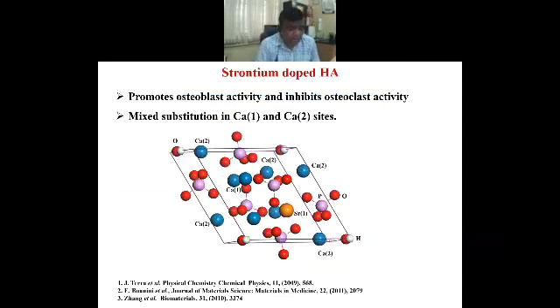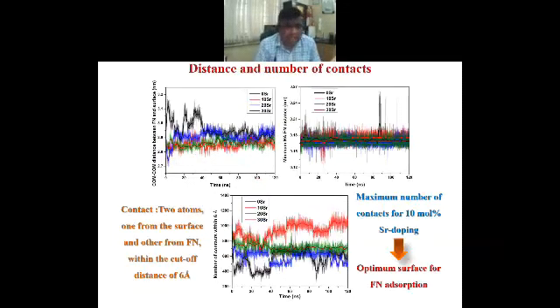Now, any dopant you add to the hydroxyapatite lattice can potentially substitute either calcium 1 or calcium 2 sites. This is the particular case of strontium hydroxyapatite, because it is known to promote osteoblastic activity and inhibit osteoclastic activity. Osteoblasts are the bone-forming cells, osteoclasts are the bone resorption cells. So we have done several experiments, but I'm going to show you in the next 5 or 10 minutes the molecular dynamics simulation results.